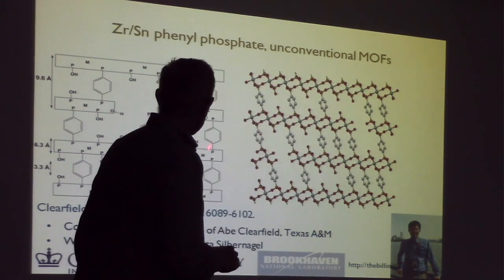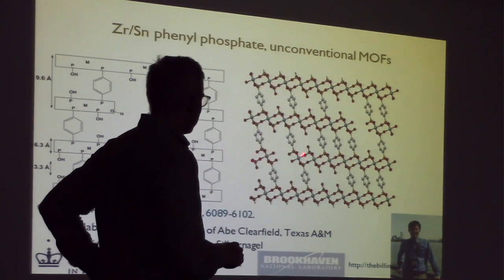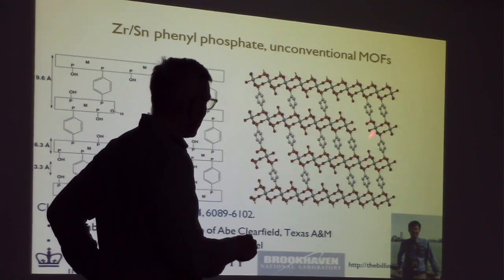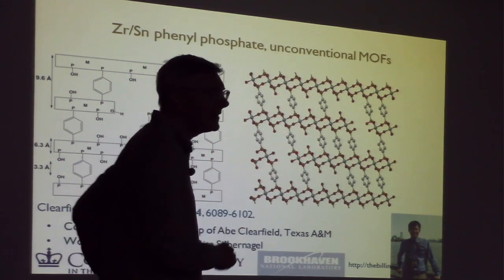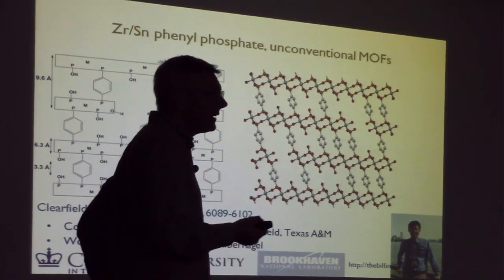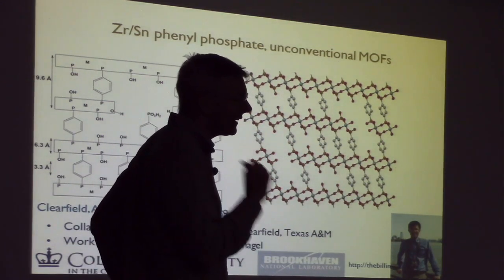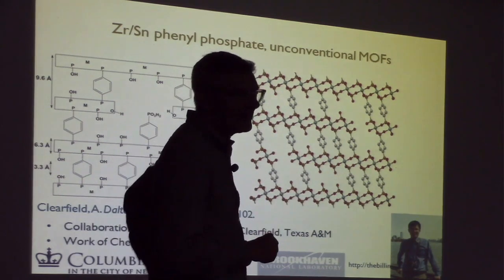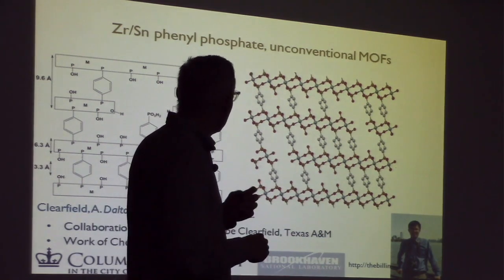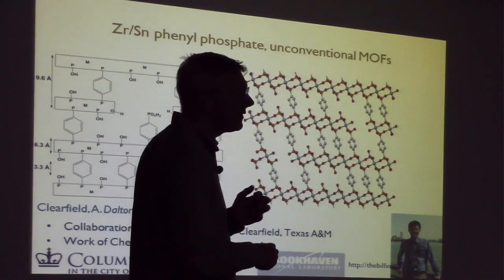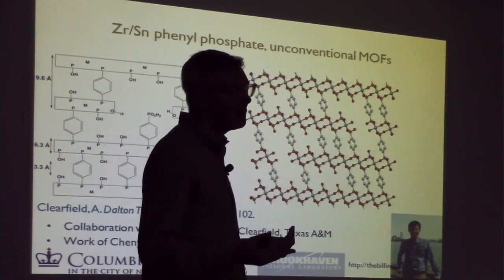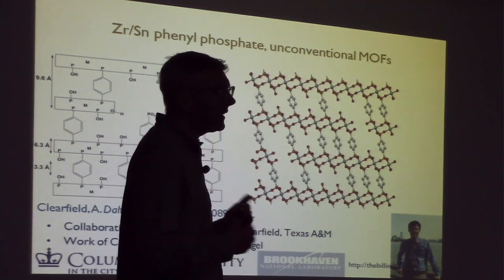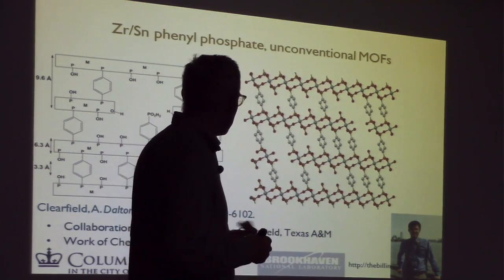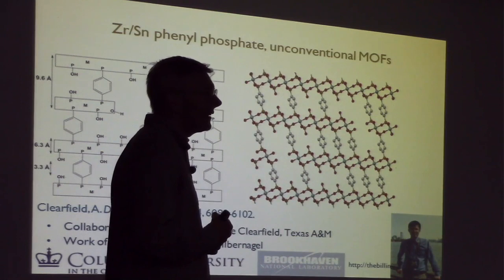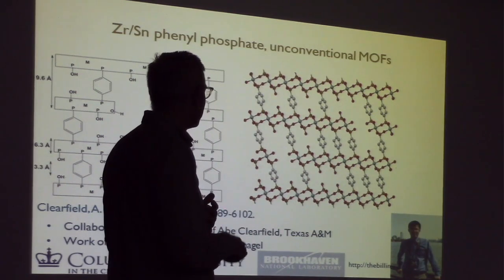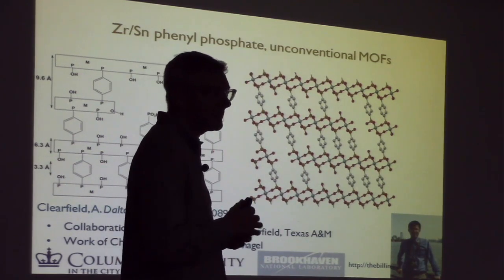So again, these things slide over each other. And this is basically Professor Clearfield's idea of how it works, that you have these defects in here and it leaves voids. And what's a little bit magical about these materials is that they're highly selective for 3+ ions. So if you have a 3+ ion, it will get trapped in this material. But if you have a 2+ or a 4+ ion, it won't. And nobody knows why the material has that selectivity. That selectivity is very important. People are interested in using this material actually for nuclear fuel reprocessing.